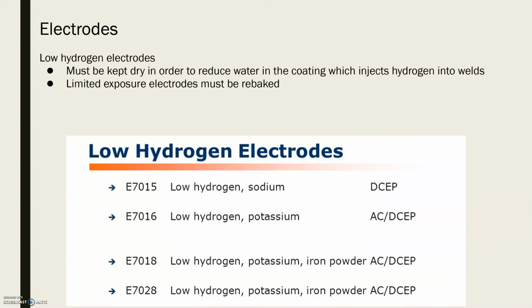Low hydrogen electrodes, also called basic, also called F4 filler material, can absorb moisture. This is why they are kept in an oven at around 120 degrees Celsius. The exposure time for 7018 is 2 to 4 hours, and 9018 limits out at 2 hours.